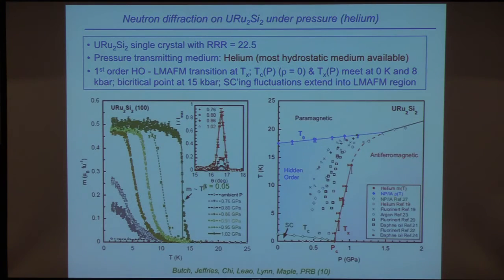Okay, and here's the proof of that. So this is magnetic moment versus temperature, again measured under pressure. And so you see that the moment, it's similar to what I just showed you. The moment here starts to increase when you get to about, let's see, sorry, 7.6 kilobars. I'm trying to convert here from one to the other. And then it starts to increase. And then it's very sharp, indicative of a first order transition. And it goes up to 0.5 Bohr magnetons per uranium.